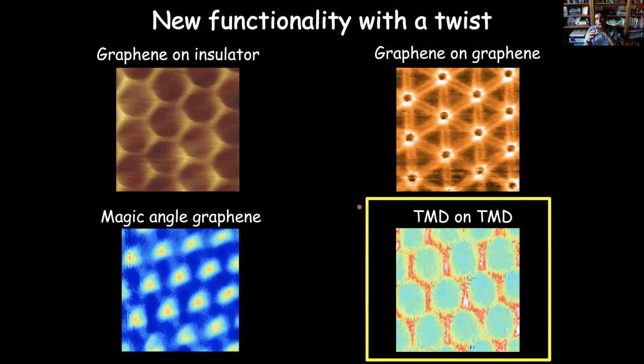And so that means that the band should be flat in momentum space to give us this high density of states, which means that in real space, it should be a localized state. And so these measurements are showing that if the density of states is high, that's when things are very localized on the AA site. Right, so there is an inverse relation there.